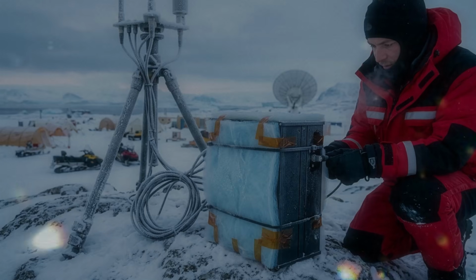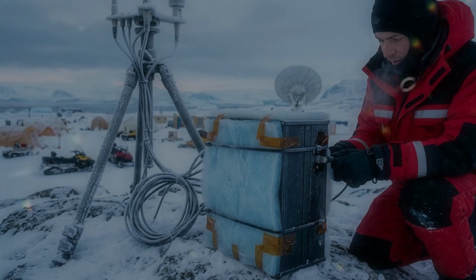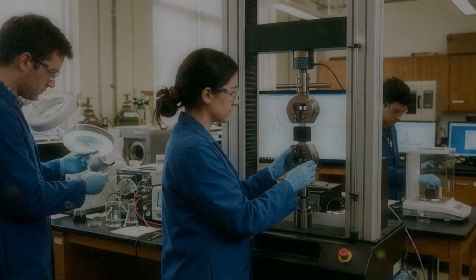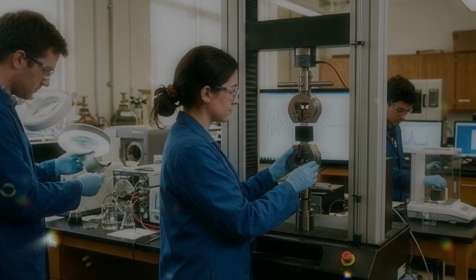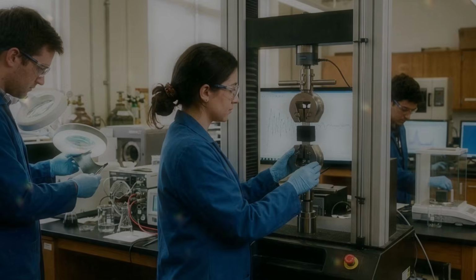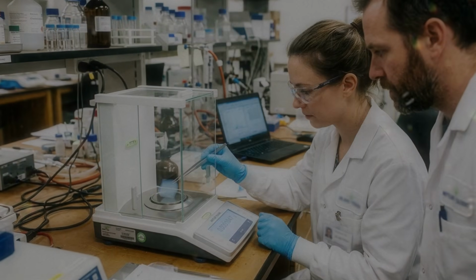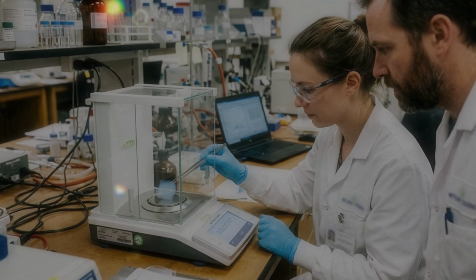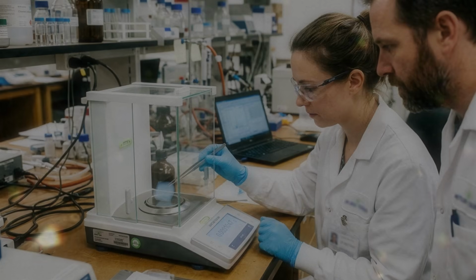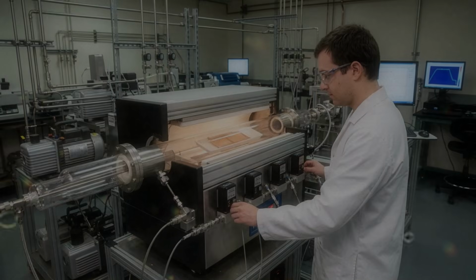Repeated compression tests reveal how well the structure survives. A good sample returns close to its original height after the load is removed. The electrical response also returns close to its earlier value. Over many cycles, some permanent change is expected. Junctions weaken, sheets rub against one another, tiny cracks appear. The sample may become slightly shorter or softer. Reinforcement can reduce this fatigue.